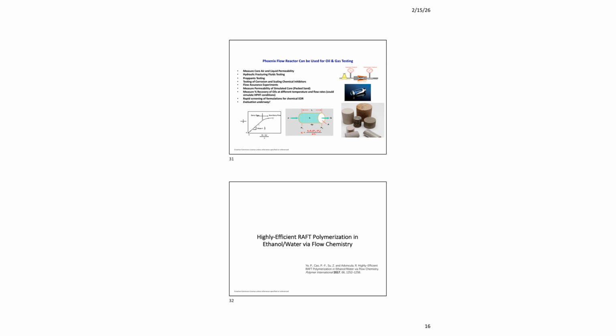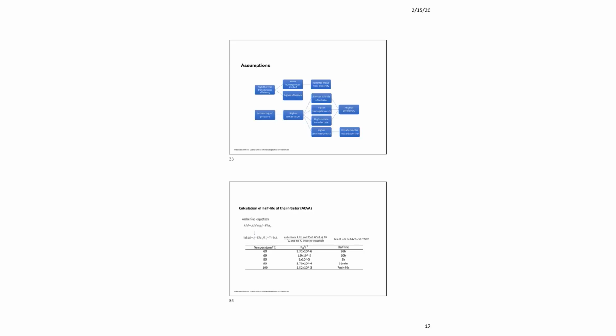Let's now dive into a specific case study on highly efficient RAFT polymerization in an ethanol-water mixture. The central hypothesis links the physical advantages of flow systems to chemical outcomes. The high thermal transmission efficiency should lead to a more homogeneous product with a narrower molar mass dispersity. Operating at a higher temperature shortens the half-life of the initiator, which in turn leads to a higher propagation rate and overall higher efficiency. However, higher temperatures can also increase termination and chain transfer rates, which might lead to a broader molar mass dispersity, so there is a balance to be struck.